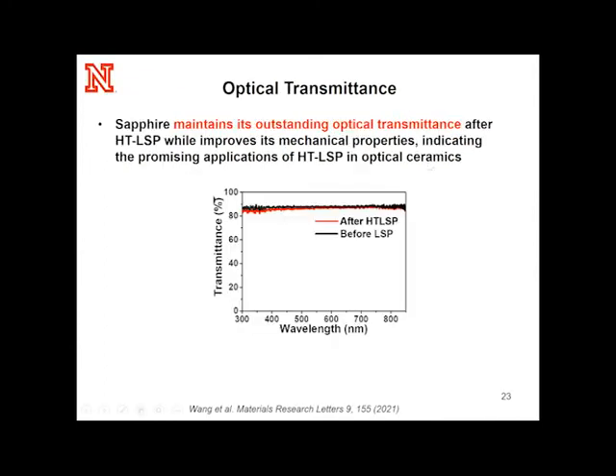Because sapphire is a very good optical ceramic, it has a very high optical transmission in a large range of wavelengths. So we are curious if laser shock peening has some effect on the optical transmission. But the results here show it's very good. There is only a slight reduction, so the optical transmission is maintained. This suggests there could be some promising application of our process in optical ceramics and other ceramic systems beyond sapphire.